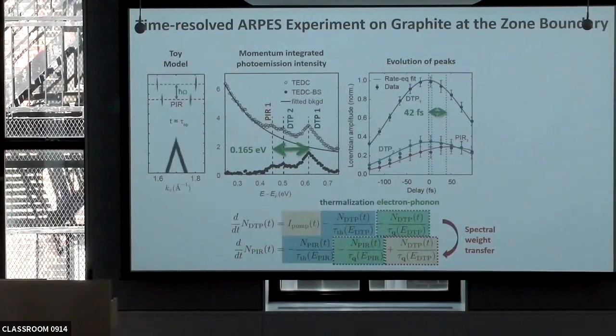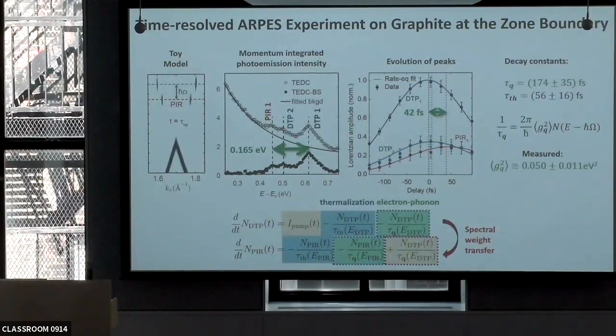By modeling this data based on this equation, you actually can come up with the curves you see underneath, and not just a guide to the eye, but a very proper analysis in terms of this equation. Then you can come up with the key numbers that we were after. Electron-phonon scattering time, 174 femtoseconds, electron scattering 56, and then using this relation, you're now extracting the g q squared of 0.050. For now, it's just a number.